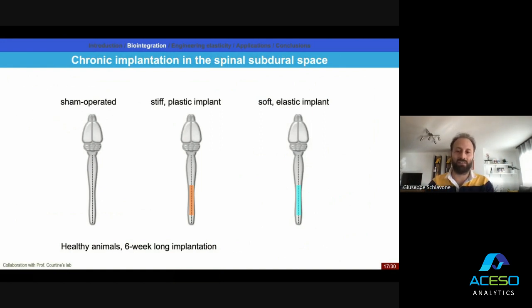This is how we proved that using soft materials actually is a good idea for the body. So we did this experiment in rodents. So the three diagrams that you see are the central nervous system of rats. So we had three populations of rats. One was sham operated. Sham operated just means that they received surgeries as if we were implanting a device, but we didn't implant any device. So it's just a control group to check what happens just due to the surgical procedure itself, without any presence of material inside. The center group were a population of rats that were implanted with a device that was actually manufactured with stiff materials. And the right group is a group of rats that were implanted with one of our devices made with soft materials.